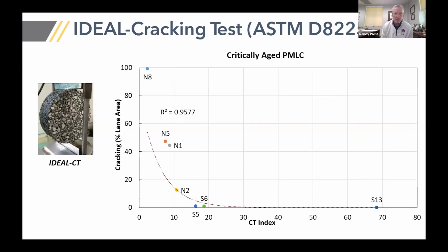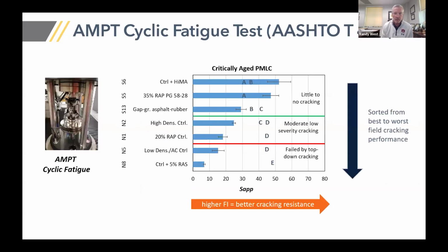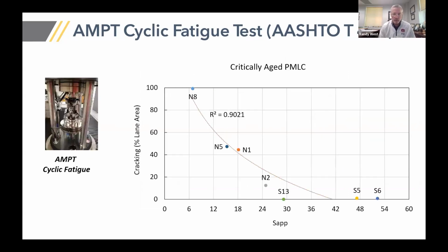The last test that we ran was the AMPT cyclic fatigue test. It also ranked the mixes correctly, as shown on this chart. And the R squared on this was really good, about 0.90.